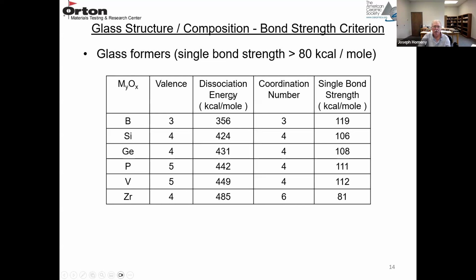And then this is the dissociation energy in kilocalories per mole for each one of these oxides. This is the coordination number. And then you divide dissociation energy by the coordination number, you end up with a single bond strength in kilocalories per mole. So all of these are over 80. So all of these are defined as glass formers.